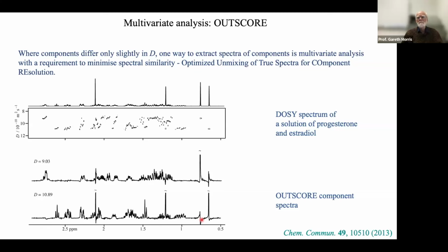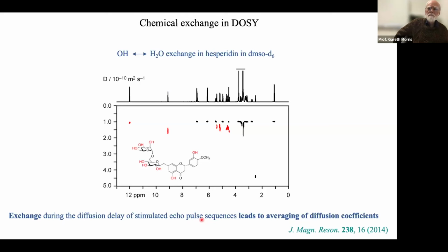Okay. We're still on misinterpretation here. What else could go wrong? The DOSY paradigm assumes that each species has a unique diffusion coefficient. And that by and large is true, but that's not true for its NMR signals. Because if we have signals which come from protons that are in chemical exchange, exchanging with a species with a different diffusion coefficient, then their diffusional decays will be different.